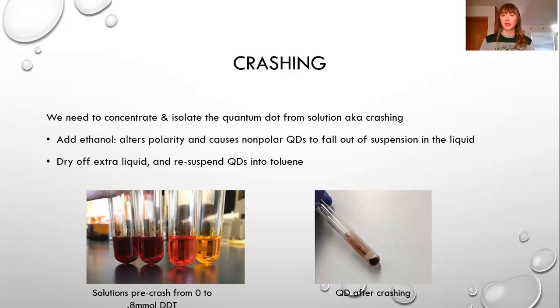It alters the polarity of the solution and causes the non-polar quantum dots to fall out of the now polar solution. We dry off the extra liquid, and it turns into this little dot that you can see on the right. It's kind of like just a blob, but it looks pretty cool. On the left, you can see these are the 4 colors that we create by using, left to right, 0, 0.2, 0.4, and 0.8 millimoles of DDT. So it's really cool. You can see not only in the data in the graph, but actually in the physical quantum dots, the differences that we're making by adding various amounts of DDT. So after we crash it, we'll suspend the quantum dots that we've isolated in toluene to make our solar cells.